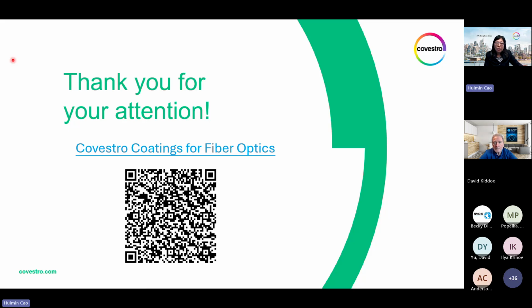It is only because at high speed, the cooling efficiency is no longer sufficient. So when the fiber goes into the die, it is still pretty hot, and the coating during the curing is still pretty high, much higher than 50 degrees C. That will indeed, in a relative sense, reduce the cure speed, but our new generation coating designed with fast cure can handle a hotter glass much better. But if you talk about optimum, faster cure speed still prefers a cooler glass.